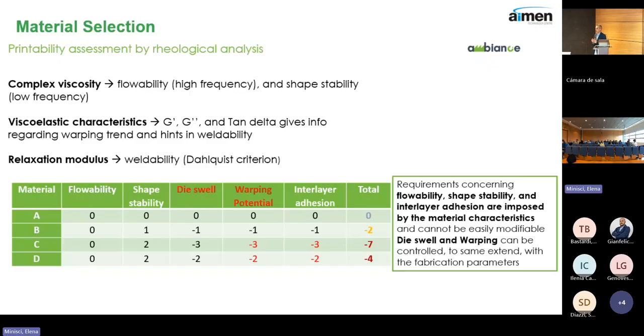So to do the assessment, basically what we have done is the following. For the reference material A, we gave a score of 0, and then for the other materials, depending on whether the performance is better or poorer than the reference material, we give a positive or a negative score. And this is what we have obtained, what I'm showing you in the table. Of course, for material A we have a score of 0, and for B, C, and D we get, in all cases, negative scores, meaning that those materials are going to be more difficult to print in large format than the reference material A. But if you look at C and D, the values we got are far more negative than in the case of B, meaning that those are the most difficult materials to print. And B is in the middle. So from a manufacturing point of view, our preferred choice is material B.